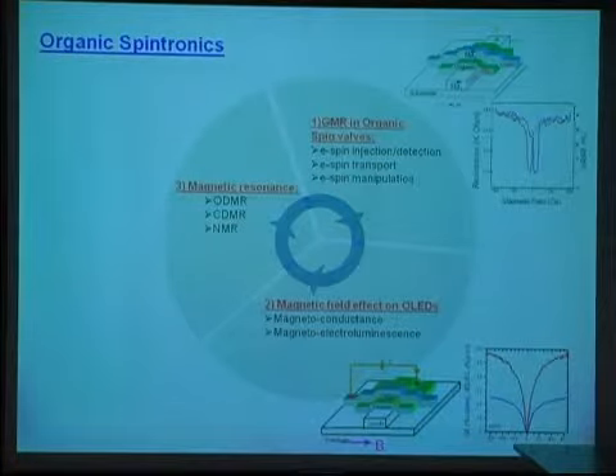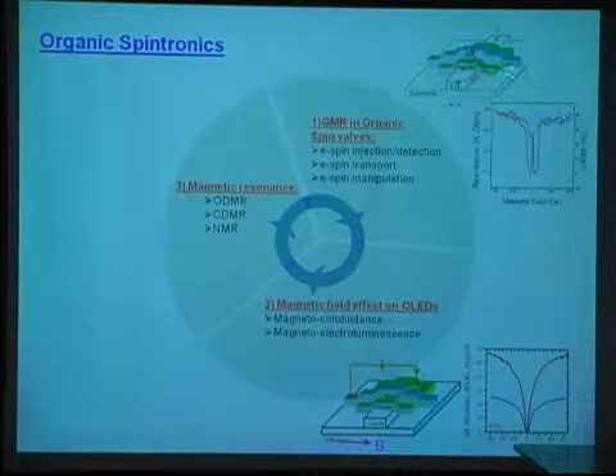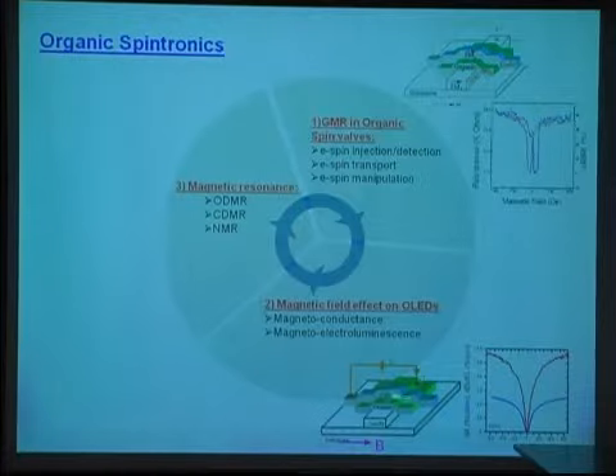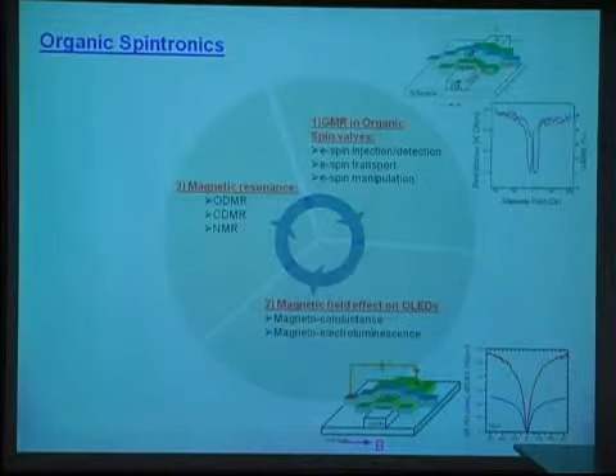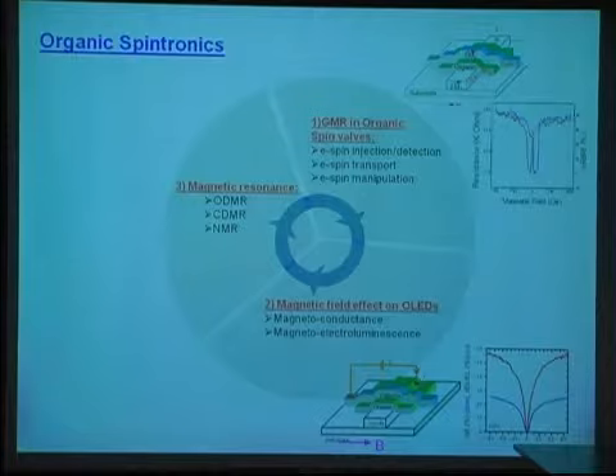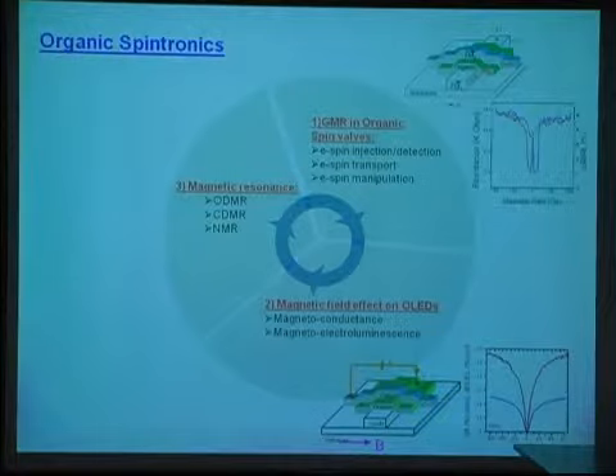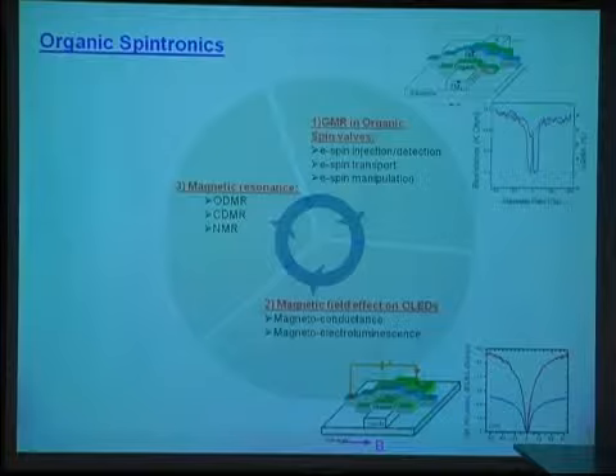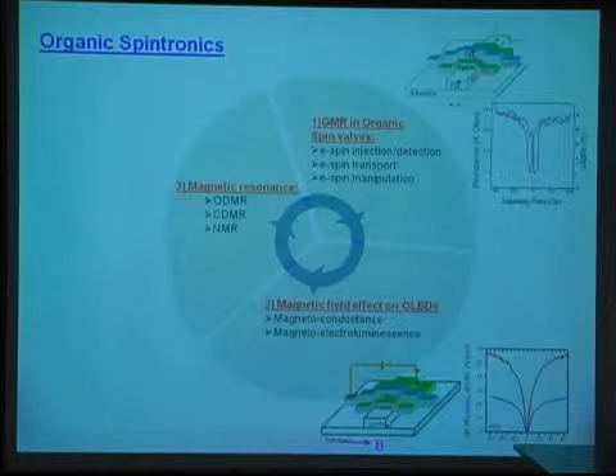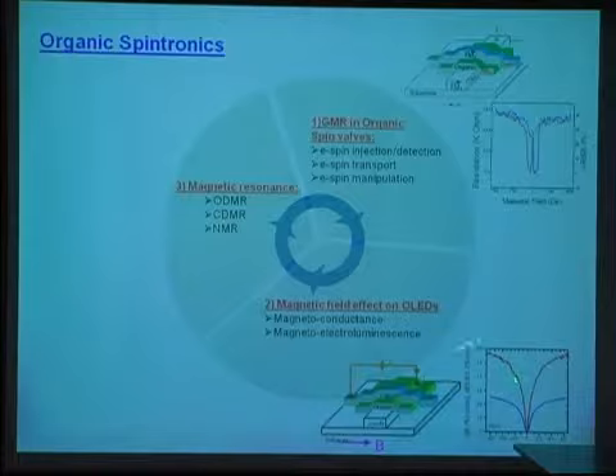The second topic that I am working on is the magnetic field effects in organic light-emitting diodes. You can see the device here is almost identical to the organic spin valves device, but here we use a non-magnetic electrode. The effect was discovered by our group at the University of Iowa in 2004. When you put the device into the magnetic environment, you can change the conductivity of the device up to 30% and the electroluminescence up to 60%. This is a surprising result, and when we reported it, no one believed us. But now it is very well known that the effect exists. In this topic I have worked for about 8 years already.